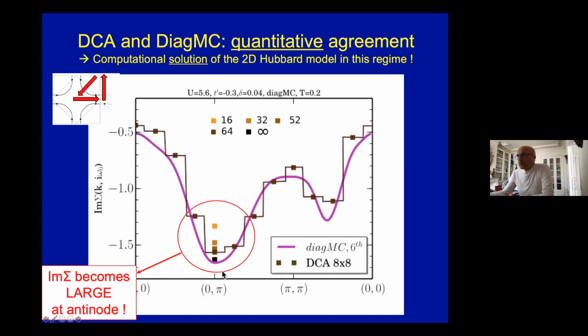Path here in the Brillouin zone, you see that here around the antinode, Im sigma is very large. That's what creates the pseudogap. And here you see that the various DCA results for different cluster sizes extrapolate to infinite cluster size exactly, within our error bars, on the diagrammatic Monte Carlo value. So this is a clear demonstration that two methods allow basically to jointly solve the Hubbard model with agreement in that regime and demonstrate the existence of a pseudogap.